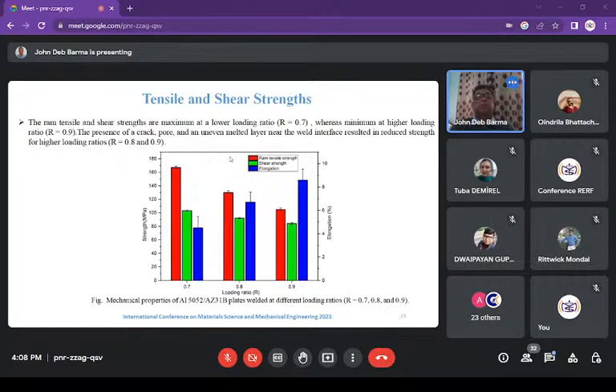Now, if we talk about the tensile and shear strengths. So we have seen that the tensile and shear strengths are found to be maximum at lower loading ratios, that is 0.7. Because you see, again, there is a relationship between hardness and tensile strength also. So tensile strength, shear strength was maximum at lower loading ratio, that is 0.7, and minimum at higher loading ratio, that is 0.9. And we have also observed the presence of crack, hole, as well as uneven melted layer, which resulted in reduced strength for high loading ratio, that is 0.8 and 0.9.